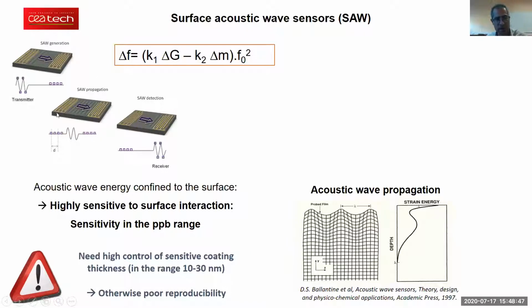What is very interesting about these sensors is that if you look at the propagation of the wave here, in this cross-section of the device, you see that all of the acoustic energy is very much confined to the surface. That means these sensors are very sensitive to what is happening at the surface of the device. This is very good because we can make very sensitive sensors, but it also has a major drawback: they are also very sensitive to the sensitive coating that we put on the surface, and we're talking here about thicknesses in the range of 10 to 30 nanometers. If we try to deposit polymers, for instance, it would be very difficult to make reproducible sensors because the thickness of the sensitive coatings will vary.